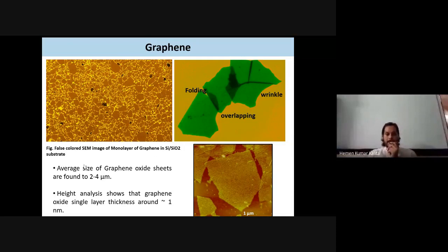So in this image, the average size of graphene oxide sheets is found to be around 2 to 4 micron, and the height of graphene comes around 1 nanometer. If you look at the bottom right hand side image, this is known as the atomic force microscopy image. This technique is used to measure the thickness of graphene. With this we can say whether graphene is a single layer, bilayer or trilayer. In this image, this is a graphene sheet, and the height.